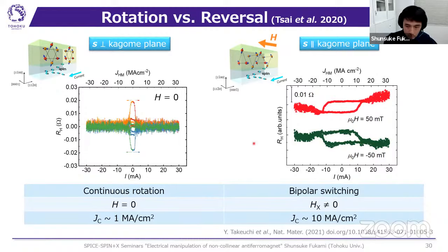To compare these two results, our chiral spin rotation shows a continuous rotation of the chiral spin structures. And for this setup, the bipolar switching is observed. And this phenomenon is observed at zero magnetic field, but that phenomenon is observed only when the magnetic field is applied along the current direction.